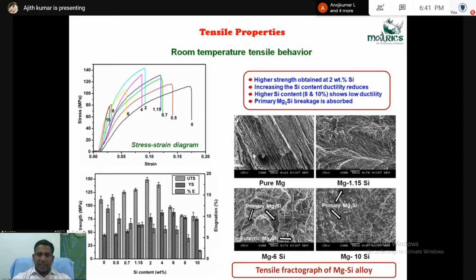So we can see the tensile property with an example. You see, with respect to the silicon addition, at 2 to 4% we are getting good mechanical property. Then we analyzed the fractured tensile samples using SEM. From the SEM analysis, we understood that there are cleavage kind of ribbon patterns, and you see in Mg6Si, particle breakage is there.